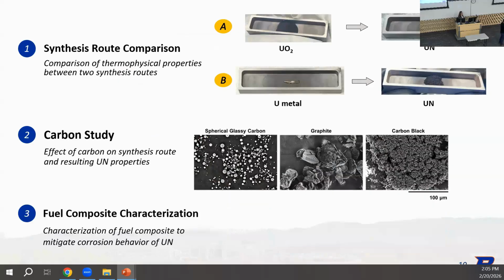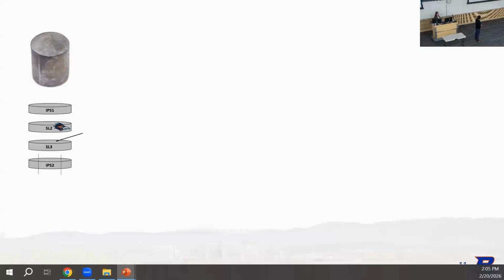Now, a third study: one of the issues with uranium nitride is its corrosion behavior. Previous studies have seen that compositing it with varying amounts of uranium diboride can help mitigate some of those corrosion behaviors. So we have an opportunity to characterize these materials. In this study, we first start the characterization process. We have a fuel pellet, or a fuel pellet size pellet, at least. And then this gets sliced up.